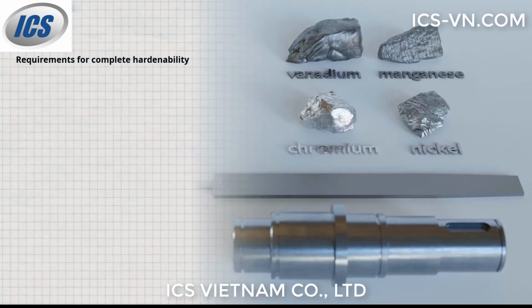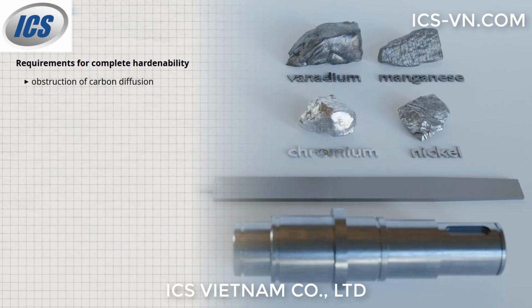To achieve hardening over the entire cross-section of the workpiece, carbon diffusion has to be inhibited. After all, the formation of martensite is caused by the obstruction of carbon diffusion during lattice transformation.